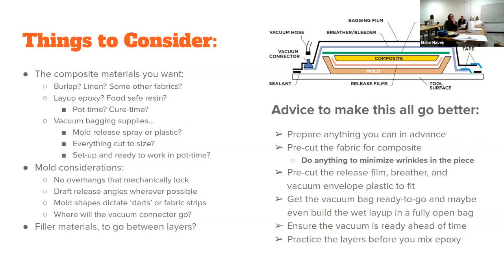The epoxy we use when we work together as a group has about an hour pot life, meaning you need to be done playing with it in an hour. There are different stages: pot life where it's actively flowing, then a tacky cure where it's safe to add another layer but won't move around, then full cure where it's totally set and you can de-mold it. So we'll mix the epoxy and have an hour to work, then 24 hours of cure time before we open the mold.